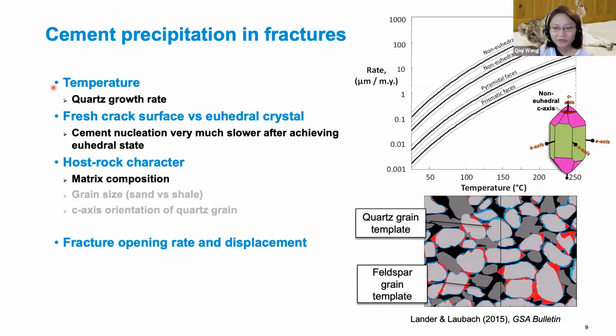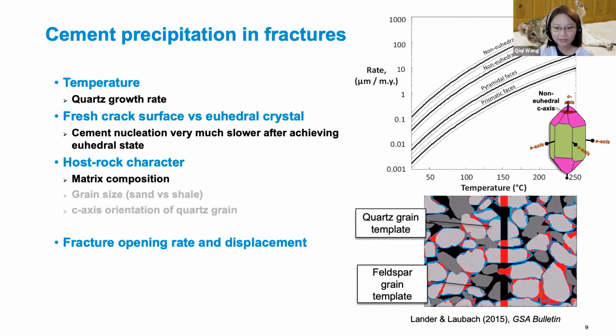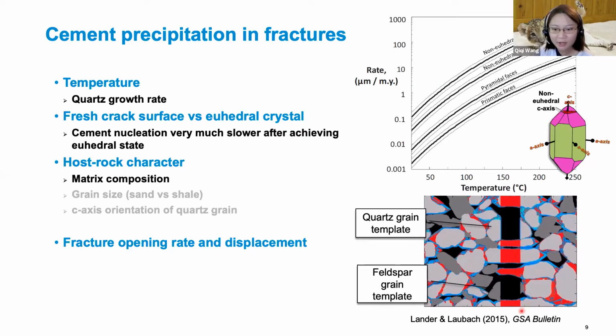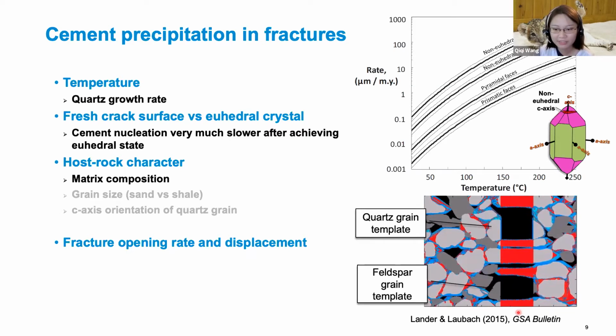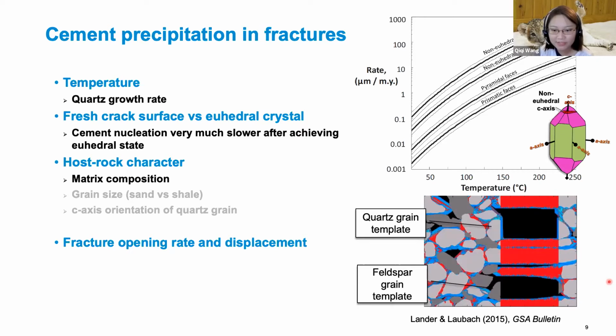And the second factor, whether the cement crystal reaches a euhedral state or not, is important, because we know cement nucleation becomes much slower after achieving a euhedral state. If you allow me to play this animation here in this corner, it's showing the opening and sealing of the fracture. You can see the rock composition matters, since quartz tends to grow on quartz, so the lighter color grains are the quartz. We see pore space associated with non-quartz grains in the rock. Actually, according to Lander and Laubach, the grain size and the crystallographic orientation also matter, but we do not discuss them in this talk. So back to this simulation, it reveals there's a competition between fracture opening and quartz cementation. We can play this again.